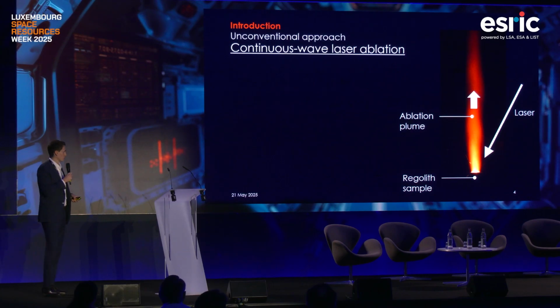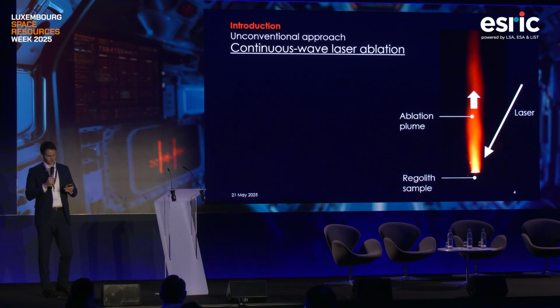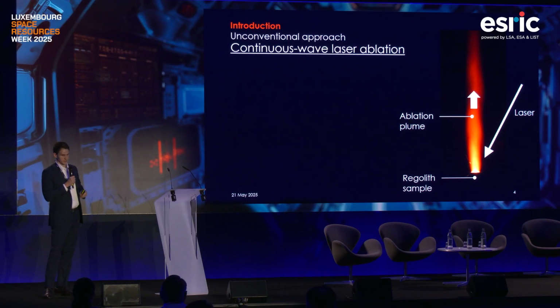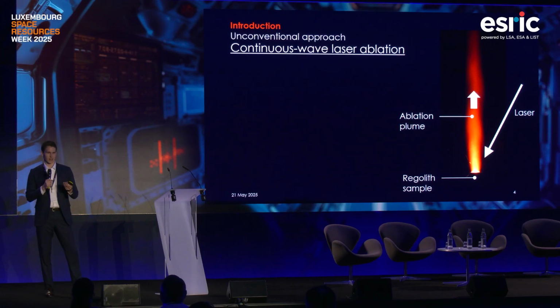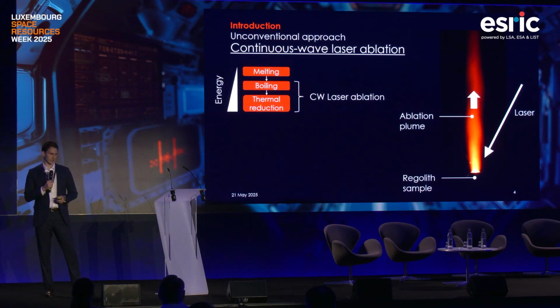And the approach that we take is rather unconventional. We propose the use of continuous wave laser ablation at atmospheric pressure. And the idea is to simply irradiate a laser continuously onto the regolith. What happens is that we deposit lots of energy inside the regolith, and it ejects a sort of ablation plume that consists not only of vapor, but also of reduced species, because CW laser ablation covers the boiling area, but just as well goes into pyrolysis, so into decomposition and reduction.